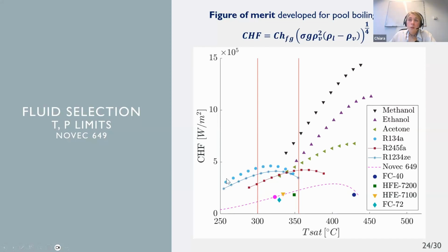And of course, there are huge differences, but in this plot, we don't see the operating pressure. So for example, for refrigerant fluids such as R134a, R245, and R1234ze, these three curves show a critical heat flux much higher than NOVEC, that is the pink curve, but they have to run at much higher pressures. Then, for example, methanol and ethanol had some flammability issues, as well as acetone.